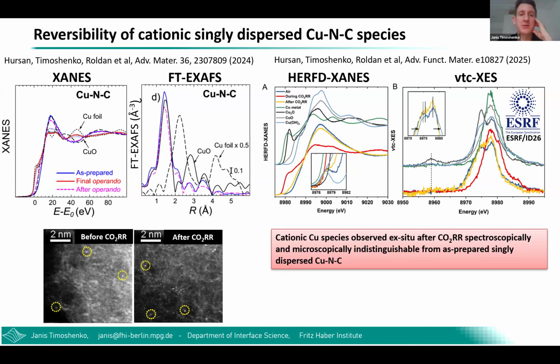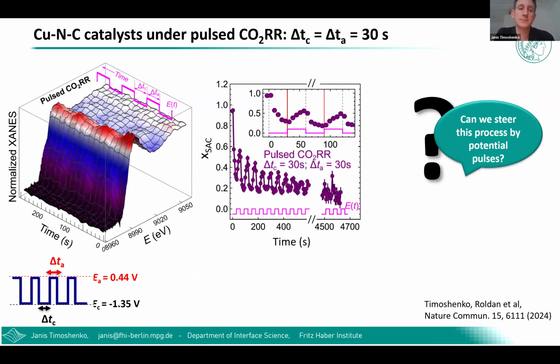So we have a highly switchable system, which can be switched between the metallic state and cationic state back and forth, basically as many times as we want. So of course, it was interesting for us to see whether we can manipulate the system using our potential pulsed reaction protocols.